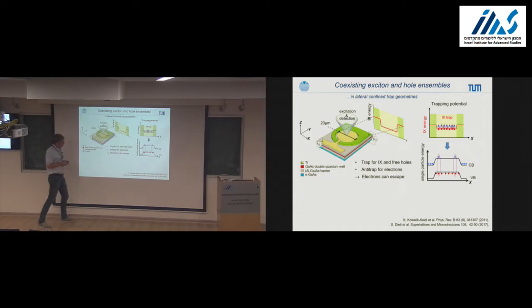But what I would like to point out: you have extra charge carriers, predominantly holes in the traps, and electrons outside. And I would like to make a comment. Please don't start immediately. This also occurs for no traps, because in III-V semiconductors, electrons like to diffuse about 10 times faster at low temperatures than holes do, because of the different masses.